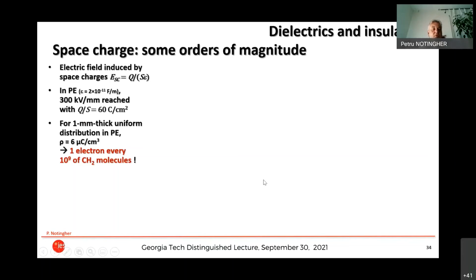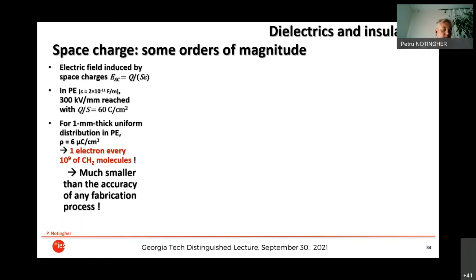Just to give you some order of magnitude, and this is very interesting because you can see what the idea is. If you consider a space charge field of 300 kilovolt per millimeter, which is the breakdown field in polyethylene, this will be the equivalent, for a 1 millimeter thick uniform distribution of charge in polyethylene, of only 1 electron per 1 billion molecules of ethylene. So you have 1 electron for 1 billion molecules. It is clearly much smaller than the accuracy of any fabrication process.